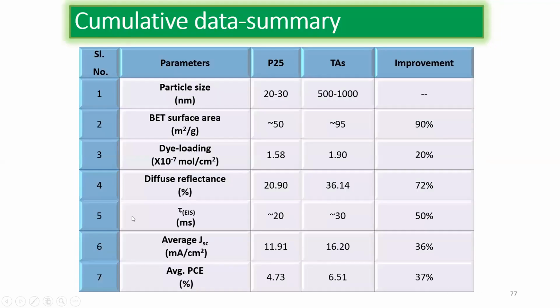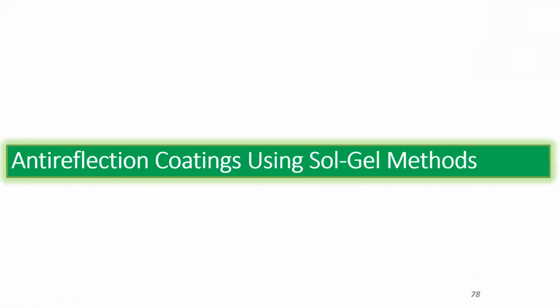So overall, the summary of the material that I have synthesized: the surface area improved by 90%, dye loading improved by 20%, reflectance improved by 72%, and because of all these things, the efficiency improvement I got is around 37%. So this is the general research of my title, hybrid nanomaterials and some technologies.